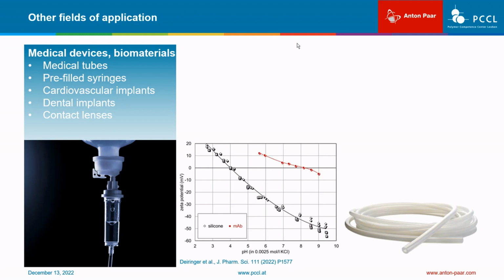The Zeta potential of a liquid dispersion of a corresponding antibody was determined by the complementary method of electrophoretic light scattering. The isoelectric point at higher pH is typical for a monoclonal antibody, and it offers a high sensitivity for the Zeta potential to detect antibody adsorption on material surfaces such as polymers, but also glass or metal surfaces.